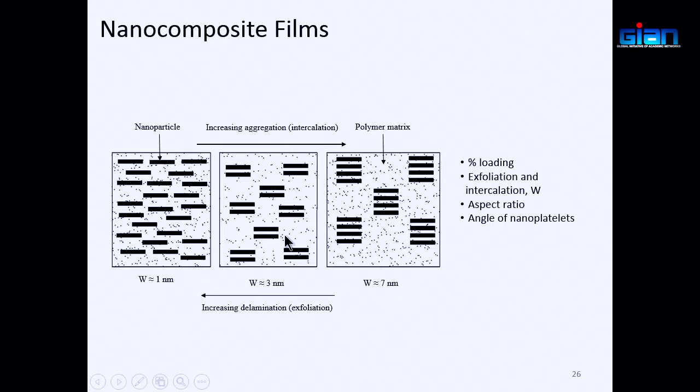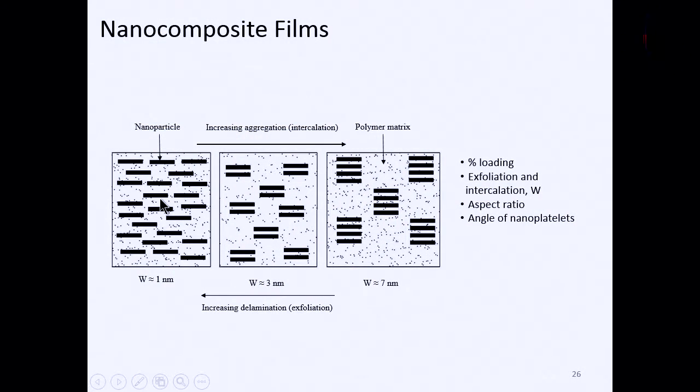The assumption is that the nanoparticles would mix well within the melt, although in practice they do not mix very well — which is why you tend to get aggregated arrangements rather than well-dispersed ones. As the melt flows, shear forces are expected to align the nanoparticles with the flow direction, so we hope they form a horizontal structure embedded within the polymeric film thickness.